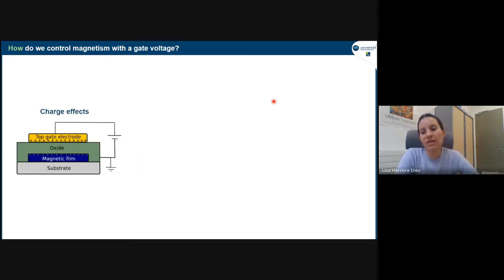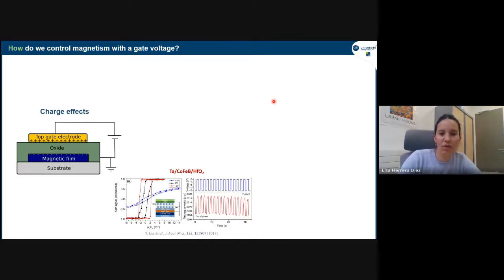So before I go into the ionic effects, let me give you an overview of what has been done with charge effects, because I will not talk about it today, but it's a very interesting side of electric field control of magnetism. So, for example, here we were able to show a few years ago that we could nicely go from out-of-plane anisotropy to in-plane anisotropy in cobalt iron boron MgO. And with this effect, we could show that if we kept a magnetic field applied constantly out of plane, we could actually toggle the magnetization from in and out of plane with only the action of the electric field.